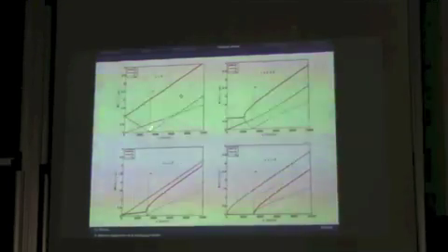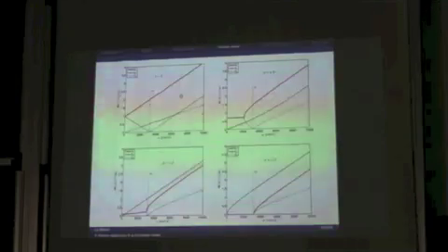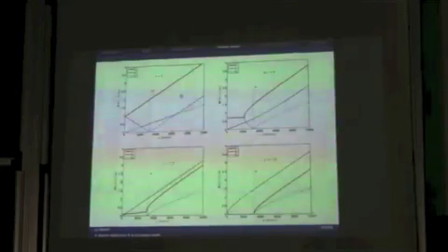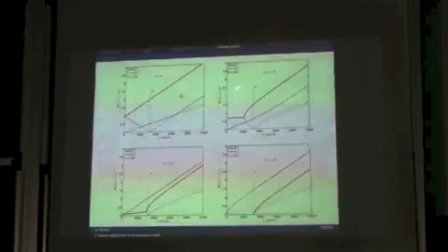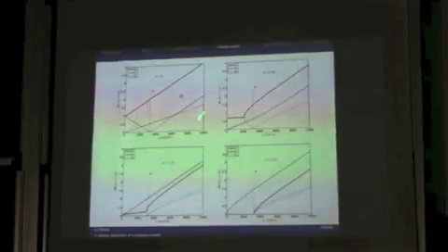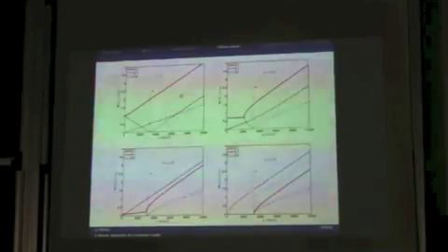This line corresponds to the longitudinal wave without defect. But if I move and see which plane wave propagates with a small angle according to the Burgers vector, I see that the dispersion relation changes and introduces some other wave number.